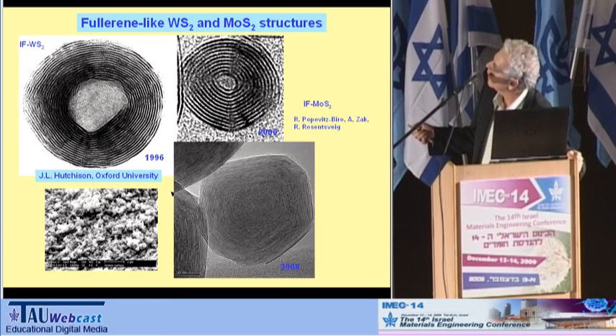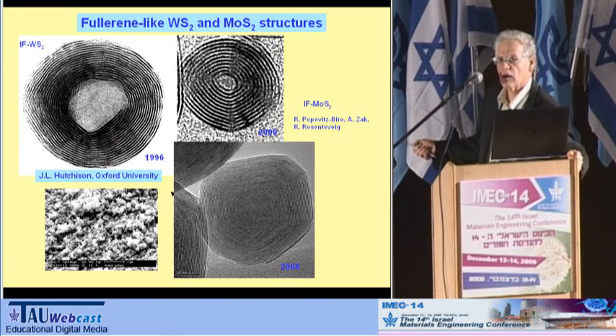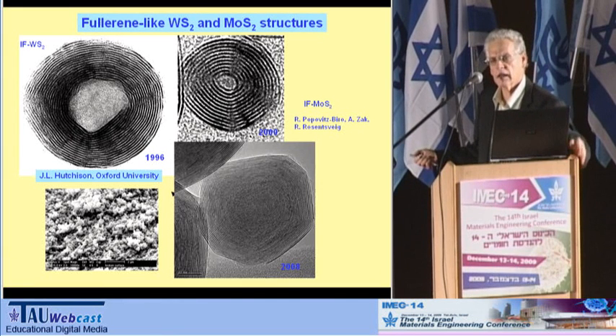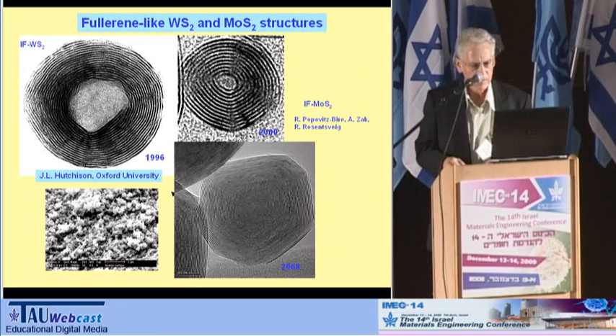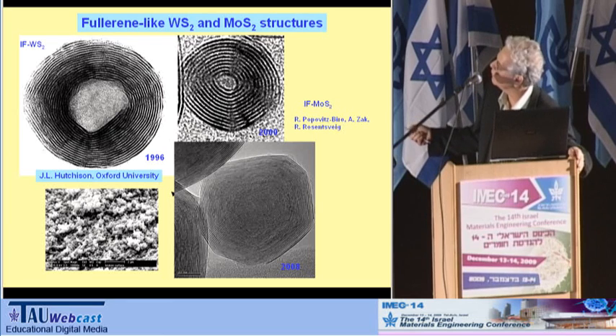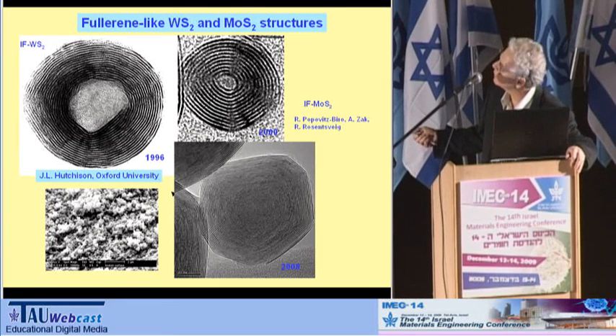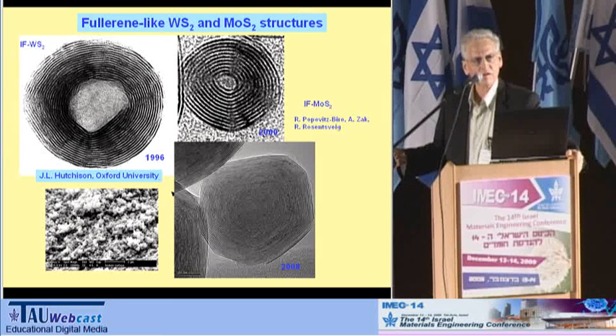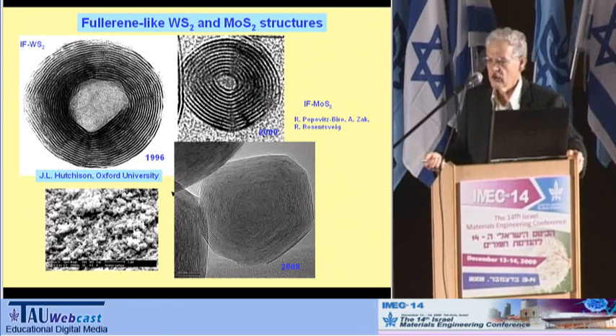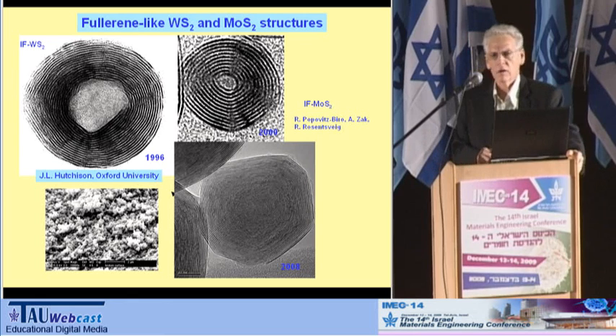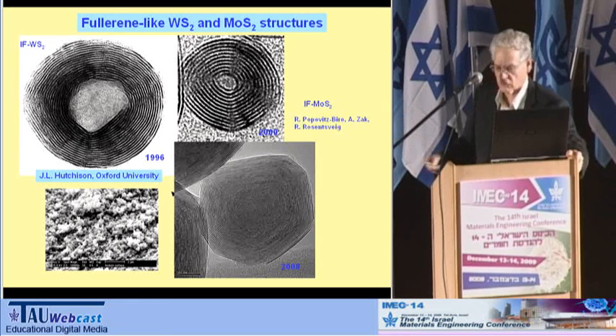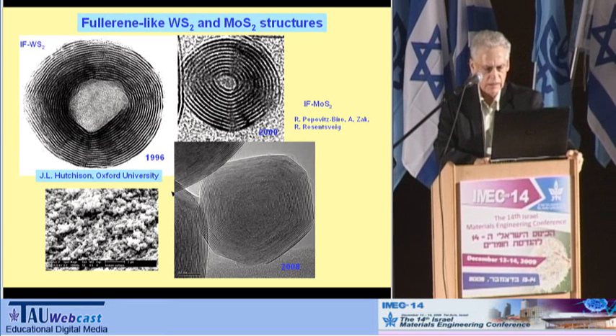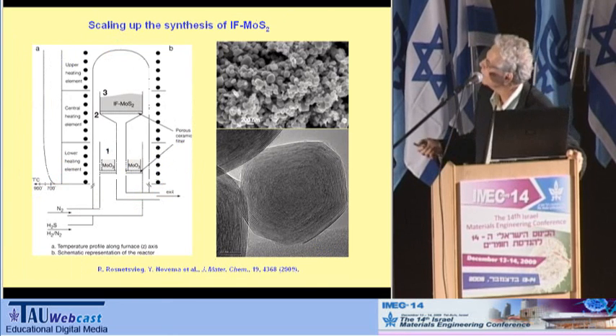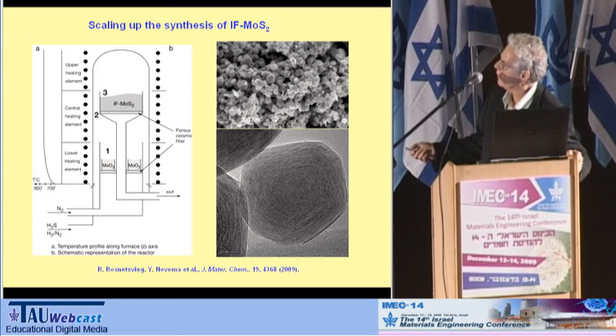Anyhow, what you see here are closed structures of molybdenum disulphide, in contrast to the well-known platelet form of the bulk material, which is basically a deck of cards. Each nanoparticle is made of numerous layers, and they are not perfect, there are dislocations, but they are all closed structures. We can make pure phases of this material with very good control on the purity and on the closeness of the structure, without a single platelet in the entire bottle.